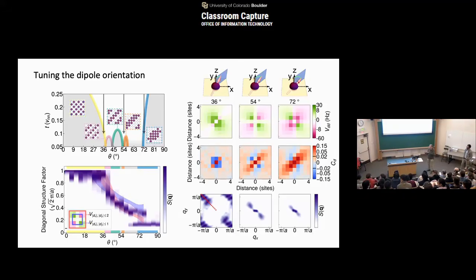So these patterns can form differently, and in fact, we do see them randomly, right? So there's a spontaneous symmetry breaking, and that's why I would call it a solid. Of course, there is still the lattice, but there are different patterns you can spontaneously form. Does it make sense? And then as you do the phase transition, the complexity arises as you start forming these patterns, you're very much in a superposition at first of different possibilities, and then you settle into one. Like odd and even stripes, as those stripes start to form, there's a lot of quantum fluctuation, very strongly correlated things happening at that transition, right?